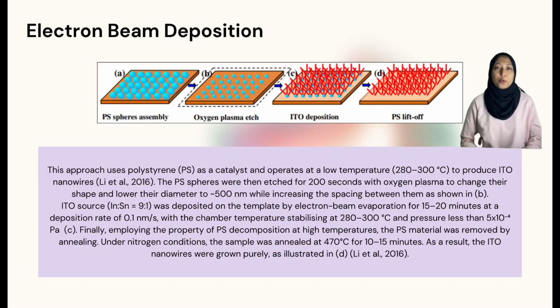The figure shows the process of e-beam deposition. This approach uses polystyrene as a catalyst and operates at a low temperature to produce ITO nanowires. Figure B shows the PS spheres were then etched for 200 seconds with oxygen plasma to change their shape and lower their diameter while increasing the spacing between them. Next, the ITO source was deposited on the template by electron beam evaporation for 15 to 20 minutes at a deposition rate of 0.1 nanometer per second, with the chamber temperature stabilized, as in C.